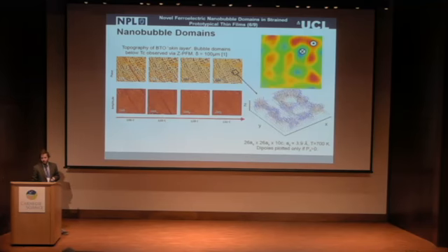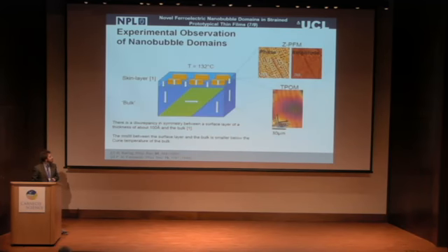Now you might be wondering, is this physical? Can we really compare this bulk experiment to our thin film calculations? And the answer is yes, we think so. Why? If we go to the work of Känzig, 60 or so years ago, way ahead of his time, he realized that in these materials you get this skin layer. So what is the skin layer? It's approximately 10 nanometers thick, and it's where the properties are distinctly different from the actual bulk of the material itself.